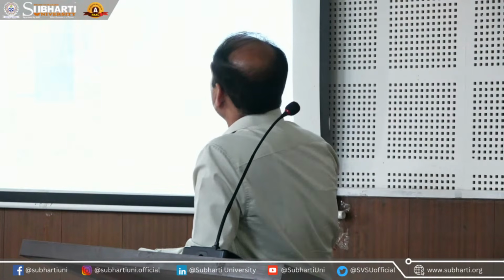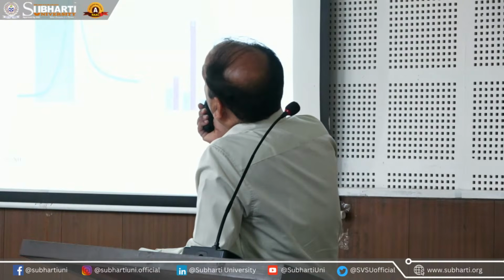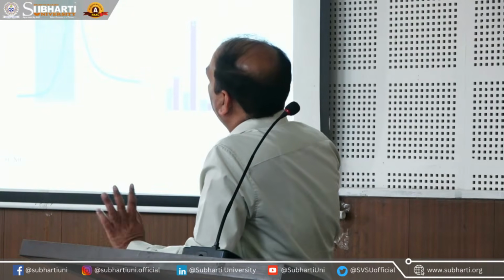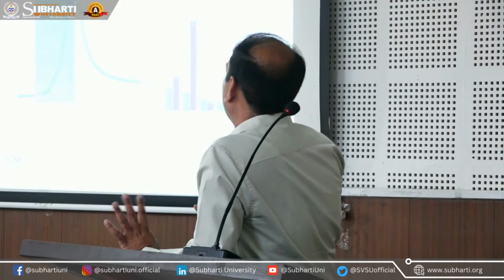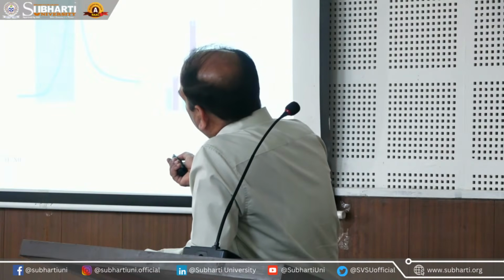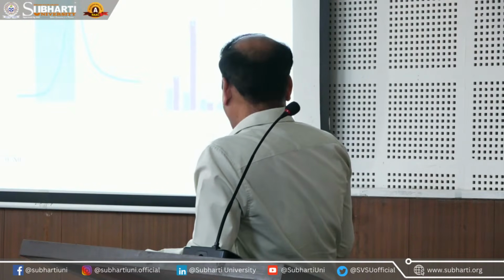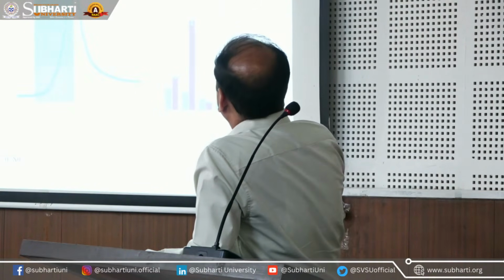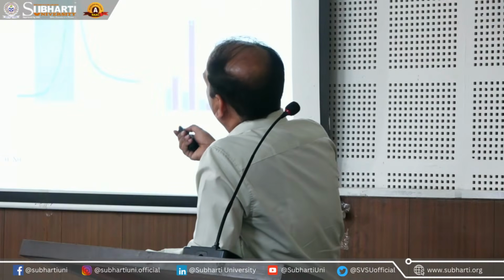In that case, we were able to measure this sensor working as a NOx sensor, meaning for both NO2 and NO gas. At 150 degrees centigrade, it is measuring NO, and this is the response recovery time we have calculated for the different samples.